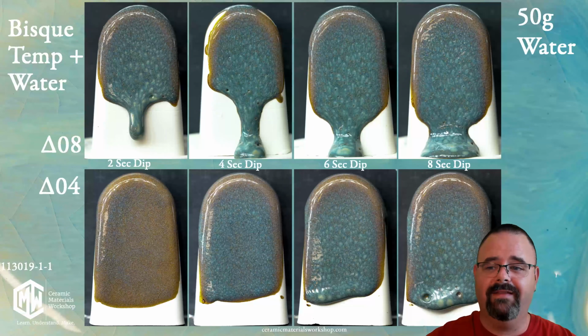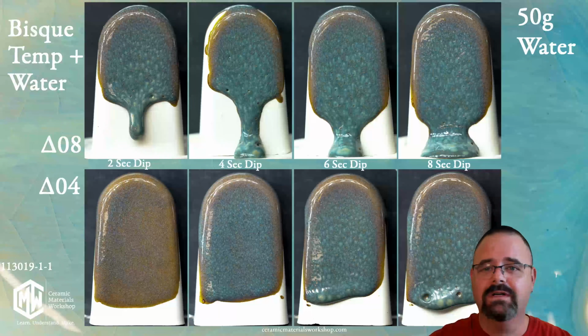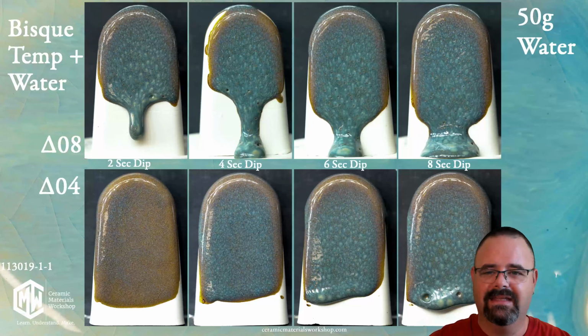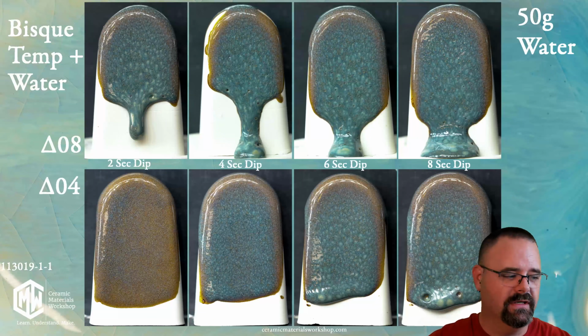You can recreate this glaze at a cone 04 bisque, but you need 4 times the length of application to get it just right, to get the number of particles you need to make the glaze work. If you're bisquing hotter, it's going to be a problem. But the bisque temperature is not the only complication.